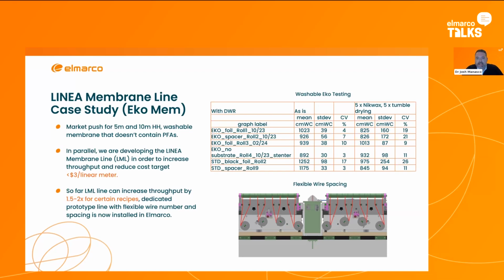So we were able to maintain, these are different examples of data on the right side, where the target was 10 meters. We were able to make materials that are around 10 meters that are still washable, that don't lose all of their hydrophobicity after laundering and drying. So we just proved to ourselves that we could do it at the industrial scale for this type of recipe, where we found that it does have an advantage to squeeze more wires into the machine to get more throughput in general for this type of system.